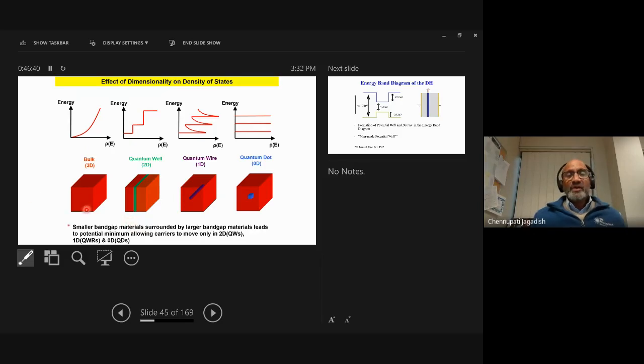So here is a case where you have a semiconductor in bulk form, and we plot the density of states as a function of energy. The density of states is the number of states available for electrons or holes to occupy. This is the case for electrons here, and it typically has a square root dependence on energy in the case of bulk. But if you put a smaller band gap material, this green material, between two larger band gap materials, for example gallium arsenide with aluminum gallium arsenide on either side, you change the density of states. You end up creating this step-like density of states.